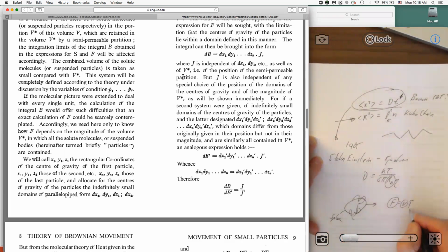Stokes came up with an equation for this friction coefficient, 6 pi times the hydrodynamic radius, which was written for a sphere. That's basically the only real equation for the drag coefficient. Any object has an equivalent hydrodynamic size for the drag coefficient. So that's the idea.